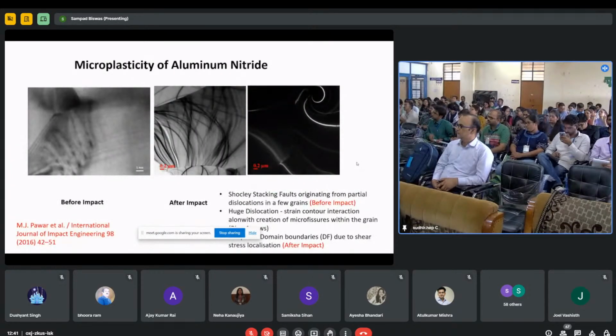So then we looked at the microstructure of the impacted ceramics. What we found is that ceramics, as I told you, is very brittle in nature, and that is due to the high Peierls stresses. And this brittleness is only because ceramics contains dissimilar ions. While metals consist of similar type of atoms, in case of ceramic crystal structure you get dissimilar ions. So when these ions move to form a dislocation, what happens? Positive ions come in close to another positive ion and it repels. Similarly, negative ions have an attraction with the positive ions. So naturally, the bonding between the ions is very strong. As a result, the Peierls-Nabarro stress, which creates the shear of the crystal structure, is very, very high. So ceramics are not at all ductile, it is a brittle material.